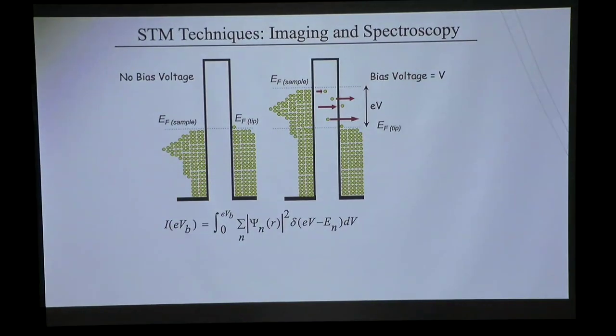So there's a very nice visual way to see what an STM measures. You can think of both the tip and the sample as a bucket of electrons filled up to the Fermi energy. And just like two buckets of water, if you bring them together and connect them together, if the level of water in one bucket is higher, then water will flow from that bucket to the other bucket until the two levels are equalized. The same thing happens to the tip and the sample. They're buckets of electrons, you bring them together, the two Fermi energies line up. The potential is the same. And then if you apply a small potential difference between them, electrons tunnel, in this case, for example, from the sample to the tip, and that gives you the tunnel current.